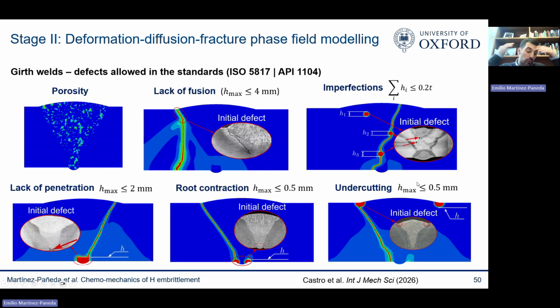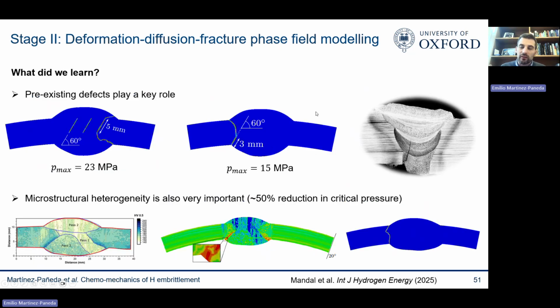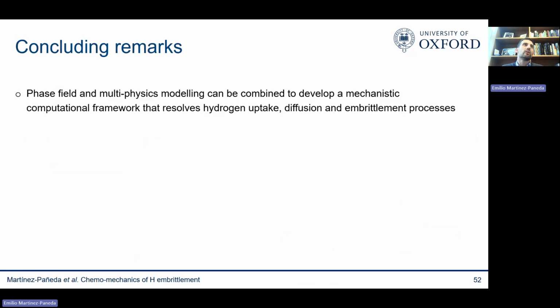So we did that, and we basically quantify at what pressures things will fail. We also try to learn things. We know that the welding standards allow you to have certain types of defects due to lack of fusion, root contraction. So we incorporated those defects that are safe in natural gas, but as we realized, they're not always safe when it comes to hydrogen. And then we learned a few things - some of the things that we learned, for example, was, of course, the defects play a big role. Microstructure also plays a big role, and residual stress is also important.